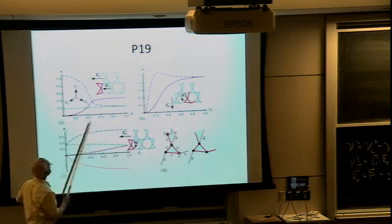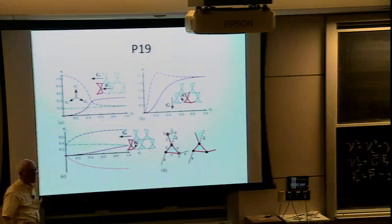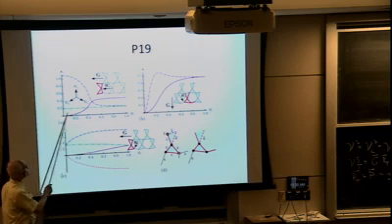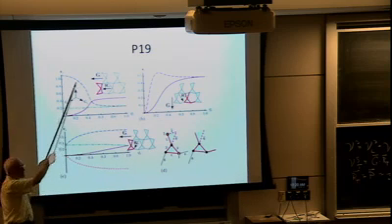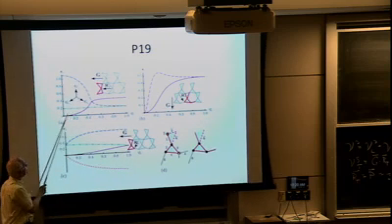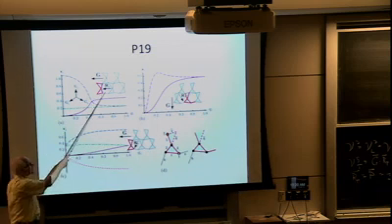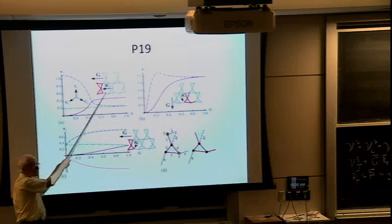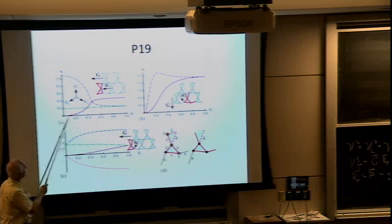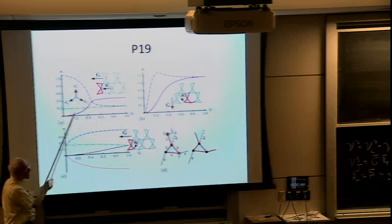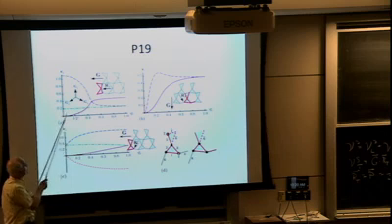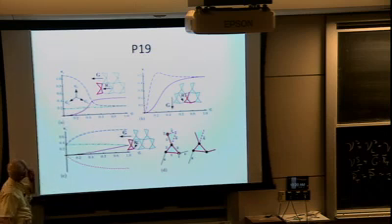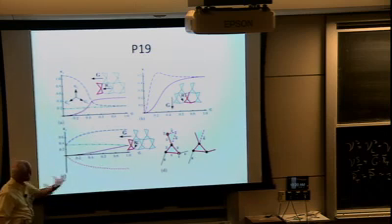And when you go through this count, you find that there are 4 zero modes on this surface. And here they are calculated. Those are the penetration depths. One of them, now this guy is not this twisted Kagome lattice. It's one of the topological ones. And the one that goes to 0 does not come in with a straight line. It comes in with a 0 slope, and that has to do with the fact that the spectrum at low